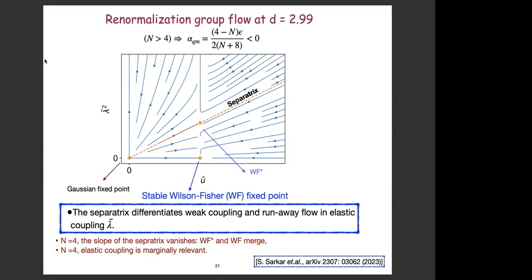Here the flow is quite intriguing. Let's see what's happening here. So again, we plot it in the lambda tilde and u tilde plane, and what we see is that we again have a Gaussian fixed point which is unstable with respect to the elastic coupling and the self interaction. But now here we have a stable Wilson-Fisher fixed point, but it is below this dashed orange line, which we refer to as the separatrix. So you can see that the flow is towards this Wilson-Fisher fixed point below this line, right?